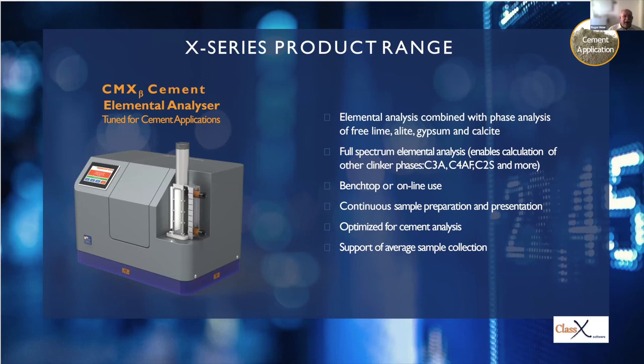And then the last system in the process, which I want to introduce to you today, is the CMX beta cement analyzer. It is a machine which is tuned for the analysis of the cement after the cement mill. It comes with a larger XRD capability, so it can measure, besides the free lime and the alite, also minerals of interest like gypsum and calcite, but it can also measure elements like chlorine. And with this combination, you have a very, very detailed look at your material, and you can tune all the parameters you would like to tune to have a perfect quality control of your final product.